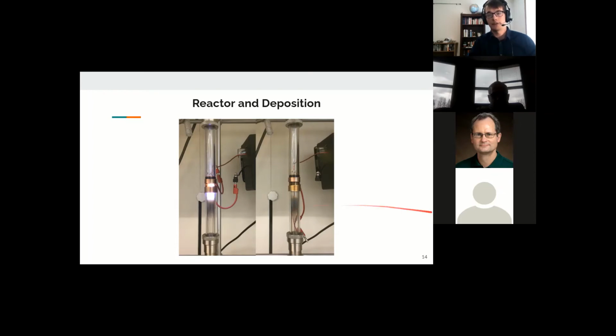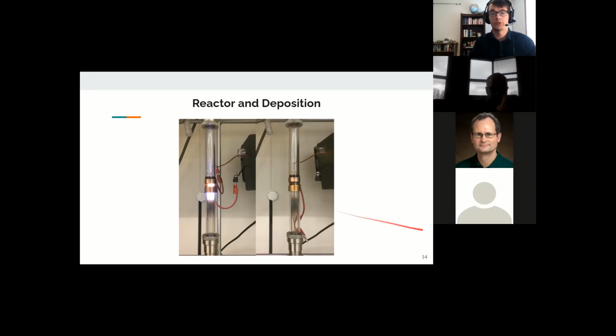And that is, as I mentioned before, because the nanoparticles are negatively charged, and anything in contact with the plasma is negatively charged, so they'll repel each other and they won't collect there. But downstream of the plasma, that's not necessarily true. And the particles deposited downstream of the reactor represent one of the largest yield losses in the system. And it's largely unavoidable without a major overhaul to the system.